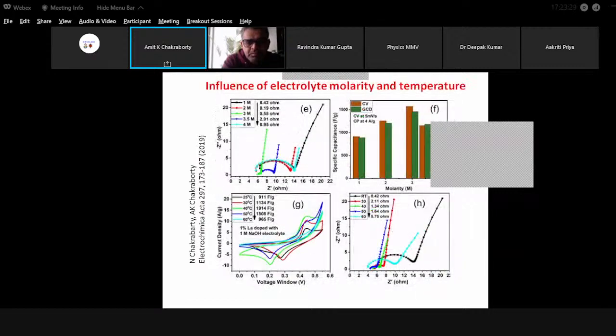So next in line is to investigate the reason for it. So again, we do the EIS of different concentrations, and we find that at 3 molar concentration, the charge transfer resistance is least. This is about 0.58 ohm. The curvature of the semicircle is almost invisible. So it's very low resistance. And that is the reason why we get such high specific capacitance.